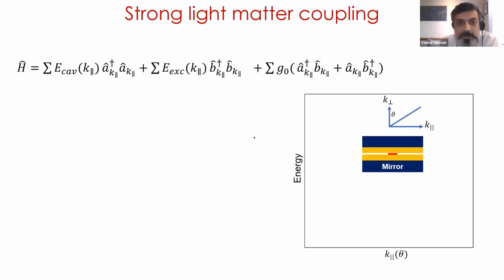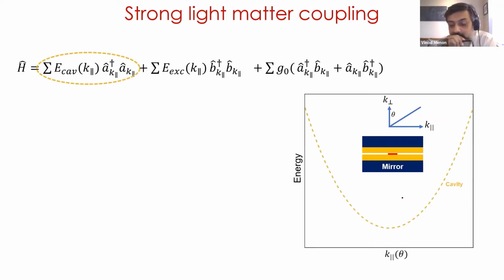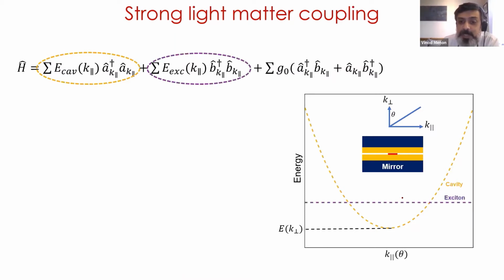So how do we look at it? Here is your Hamiltonian all written out. If you take this, that's your dispersion of your cavity. The cavity dispersion has this parabolic shape within the small wave vectors that we are interested in. Within the same range of wave vectors, if I look at the exciton resonance, you can treat it as a flat resonance or flat dispersion, because the wave vectors that we are using here are much smaller than the wave vectors at which the exciton would actually show some dispersion. So everything we are seeing here, the exciton can be treated as a flat dispersion.